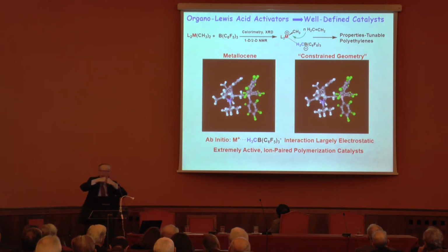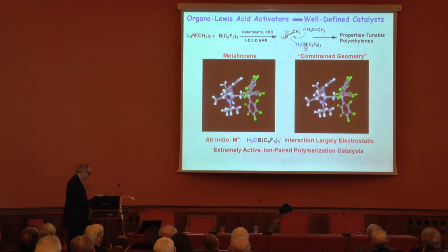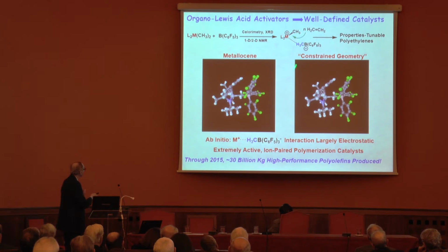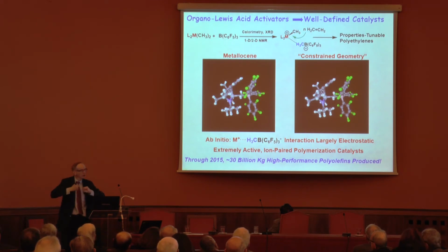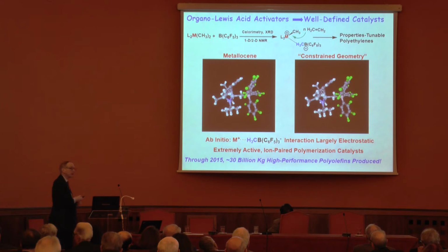Really important for chemistry. It's hard to stretch two-electron, two-center bonds. Remember the Morse curve. But electrostatic systems are very, very flexible, and we can see by computation the olefin inserts and grows a chain. Alessandro Motta, one of our Italian collaborators from the University of Rome, is in the audience, and has been very important in this. So this particular catalytic system, we partnered with Dow Chemical, and to date they've made about 30 billion kilograms of polymer, of plastic, very high grade, very strong, very flexible, very tailorable, using our catalytic chemistry. This is about $100 billion worth of sales.